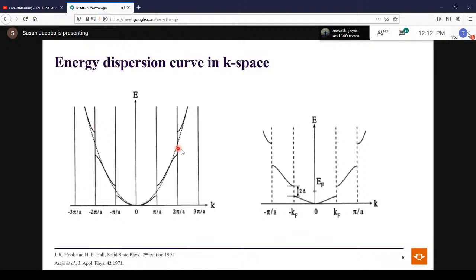What happens then once the spin density wave is formed? Here we have the one-dimensional energy dispersion curve in reciprocal space or k-space. We have energy gaps at the edges, the boundaries of the Brillouin zones. Once the spin density wave is formed, you're introducing an additional magnetic periodicity into the lattice. As a result, you have an additional energy gap 2Δ that is introduced into the system. As a result of that, the energy of the occupied states is lowered and the energy of the unoccupied states is increased. So there is a decrease in the density of states at the Fermi level, and the energy of the occupied states is lowered, and the spin density wave is thus stabilized.